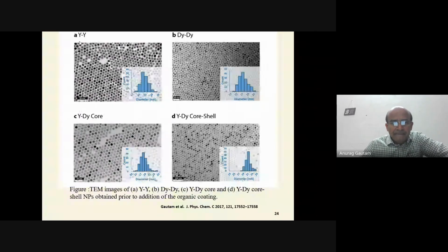So here, they have different relaxation rates. Diamagnetic particles do not relax in the magnetic field, but this is paramagnetic, so they relax. It's shown here, if we keep a certain thickness of dysprosium, let's say 2 nanometer thick dysprosium on the surface of yttrium, how much the contribution is. Or we keep again Y and 4 nanometer thick dysprosium on the surface, how much relaxation rate there is. All have been measured in this article.